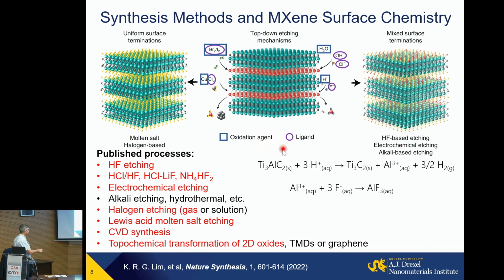Initially, Michael Naguib made them by putting titanium aluminum carbide into hydrofluoric acid, etching away aluminum from a compound known as a MAX phase. So what are MAX phases? Those are layered carbides and nitrides of transition metals. You have a layer of transition metal separated by a layer of the so-called A element: aluminum, tin, gallium, silicon. These compounds were discovered by Novotny and others in Austria in the 1960s, and my colleague at Drexel, Professor Michel Barsoum, is really a leader in the field who developed them into a materials family.